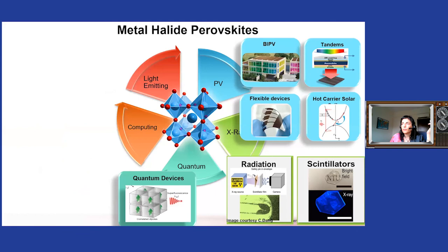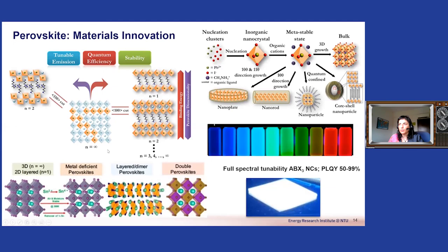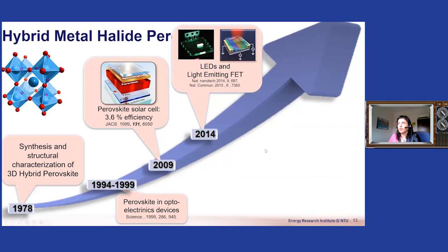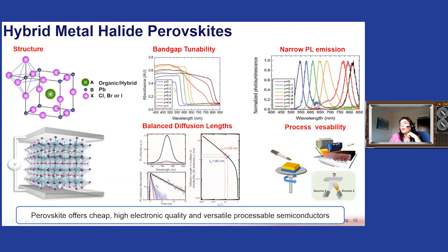So what we have seen here, maybe let's do it like this, it's even easier. What you can see here is that we are changing the composition, and we can see a clear change in absorption and in PL. For example, keeping everything constant and changing the content of chloride, bromide or iodine. The change of one of these can give this shift.